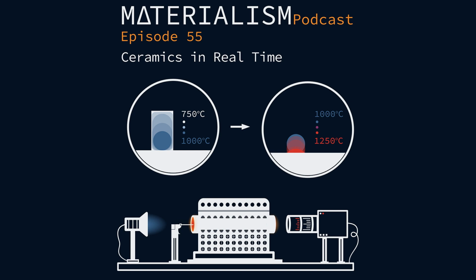So you look at the image of the shadow of your sample. And you see how it shrinks, not very well, because the resolution is not high enough. But you can see the sintering, more or less. But most of all, you see the softening of the material and the melting of the material. So it is important to identify the sintering, the melting, and for glassy material, the spherical shape. So the shape at which the surface tension is so strong that it keeps the material together.